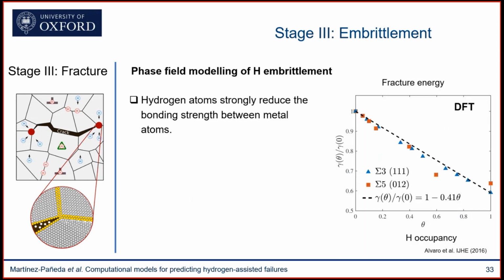The first one is that if we look at our problem across the scales, so if we do atomistic calculations, we see a very significant reduction of the bonding strength of metal atoms with hydrogen occupancy. So here you can see DFT calculations for nickel, and you can see predictions of fracture energy versus hydrogen occupancy. And you can see that this is for two types of grain boundaries in nickel. If your grain boundary is full of hydrogen, if your occupancy is close to 1, then you get a 40% reduction in fracture energy or grain boundary strength. So that's a significant one.